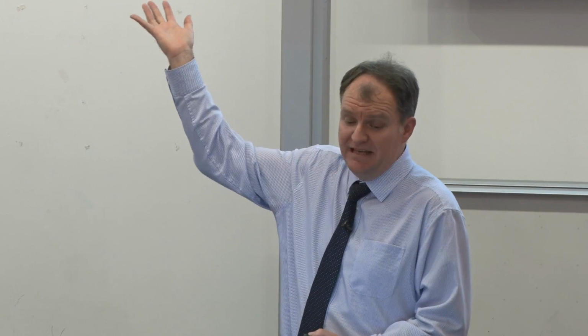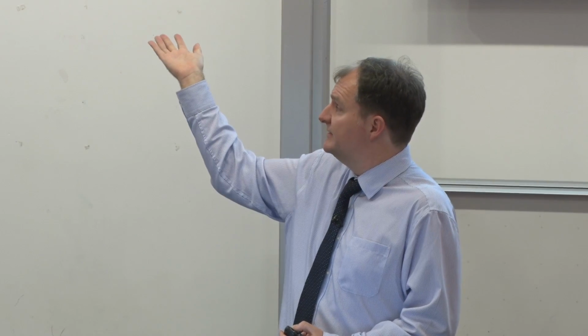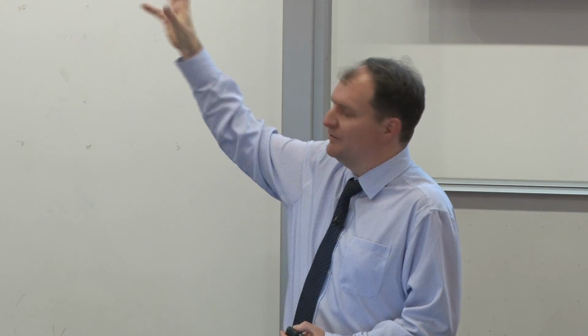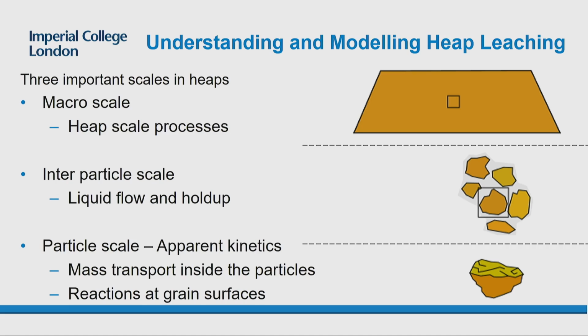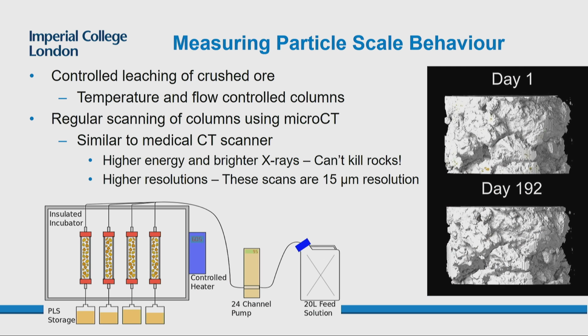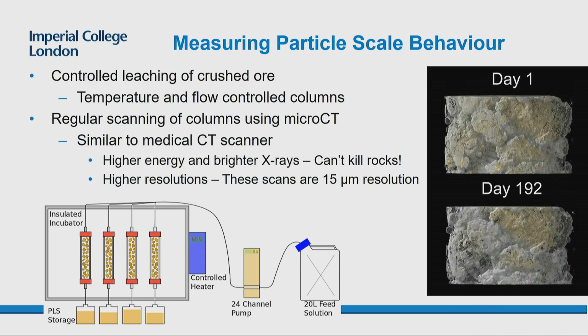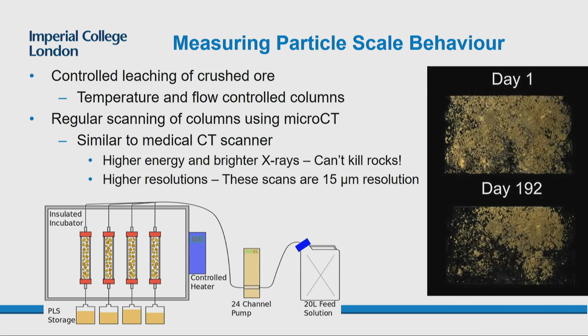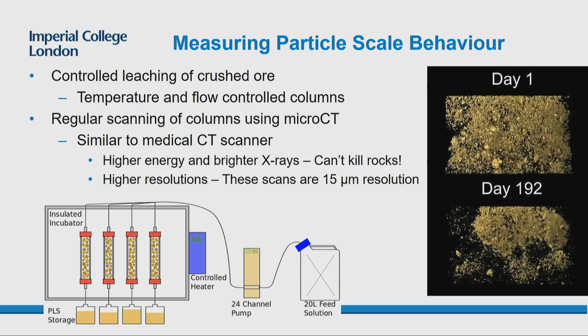And so we looked at it at a few different scales. We're looking at what's happening at the heap scale, what's happening at the liquid flow scale between particles, and what's happening down at the particle scale itself. As I don't have a lot of time for this section, I'm going to be concentrating on what happens at the particle scale. And what we did here was a lot of small-scale leaching tests, where we're trying to keep the water addition on the outside very even, and then we were CT scanning these columns.